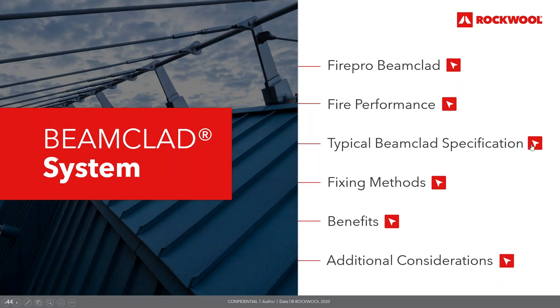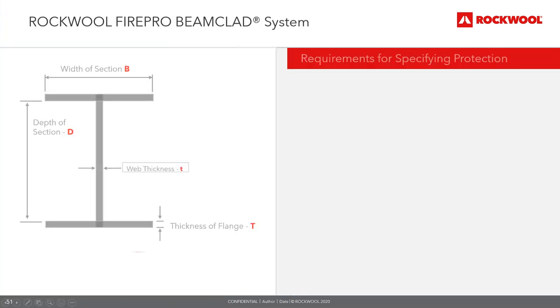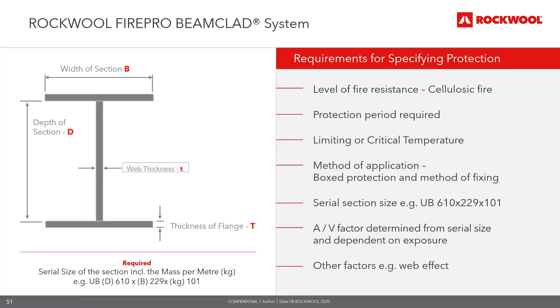Looking then at typical beam clad specification. In order to calculate the thickness of insulation for steel beams and columns, there is certain information required. We need to know what type of fire it is likely to be. Generally in buildings, we're looking at cellulosic fire protection. The fire rating that is required, so for example, do we need a 1 hour or 2 hour fire protection? What the limiting or the critical temperature is of that beam, if it's been calculated. If it's not known, then we usually fall back to the 550 degrees C limiting temperature.